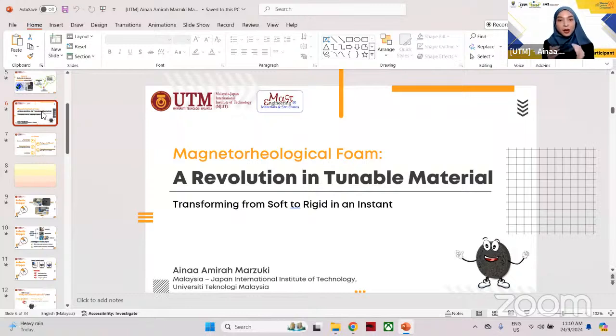So the stiffness of MR foam will not change above this magnetic field. This leads to the challenge of making sure the strength, the stiffness of MR foam is enough for use in the robotic grippers example. To overcome this, we tried another procedure by using different compositions, such as varying the concentration of magnetic particles. And we actually observed an enhancement behind the effort we put in. So this is the experience, the challenge I faced throughout my research.